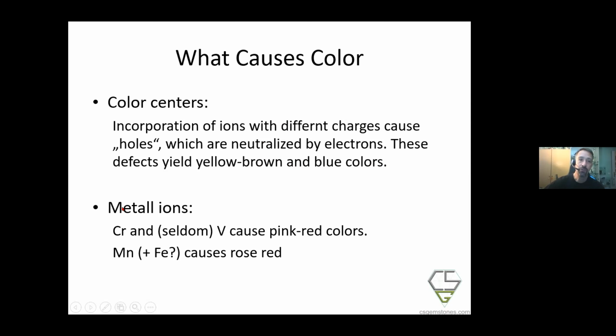Metal ions, unfortunately, are rather rare. We have the chromium or seldom vanadium that cause the pink to red colors. Very often it's hard to differentiate because whenever you have chromium, you do have a certain amount of vanadium. Typically, the chromium is in higher concentration than the vanadium, and the absorption spectra look rather different. So you have to look carefully to see the difference.